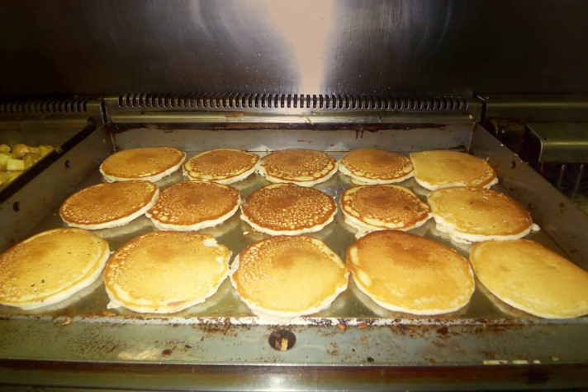If damage does occur to the chrome surface, food acids tend to penetrate and dissolve the metal substrate beneath the chrome coating, causing it to spall off. Chrome griddles can be cleaned with soapy water and a palmetto bristle brush. Metal scrapers and abrasives should be explicitly avoided, as they tend to damage the surface and permanently cloud the mirror finish. Special cleaning agents and powders specifically for use on chrome surfaces are also available.